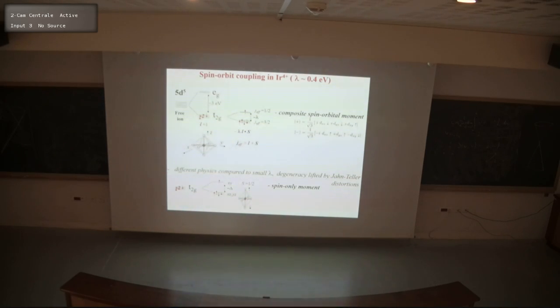For lambda positive, we want L and S to line up. So in terms of the effective angular momentum J, the ground state would be a quadruplet, J effective 3/2, and the higher state will be J effective 1/2. If we put all our 5 electrons here, then essentially we have a hole in the J effective 1/2 multiplet. What's important here is that, contrasting to the situation down here where there's an orbital singlet ground state and a spin-only moment, here the spin and the orbital part are strongly entangled with one another, in the sense that if we pick one of these two representatives of this Kramers doublet, then spin up would correspond to a certain orbital and spin down to certain other orbitals. So the spin knows about the orbital motion of the electron.